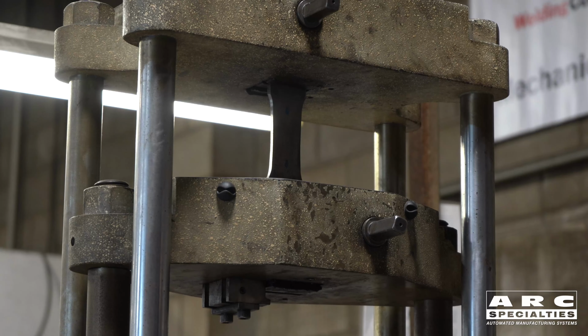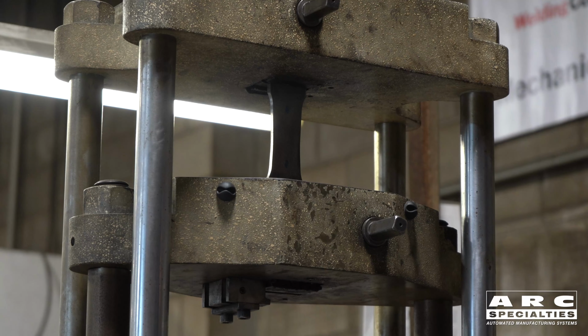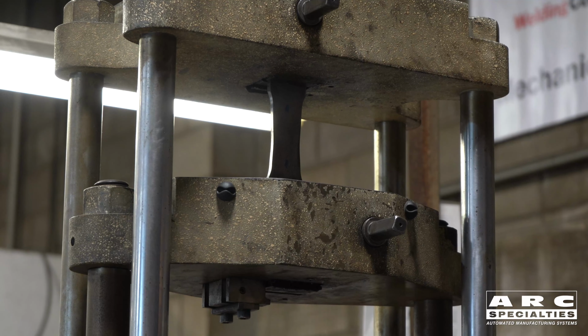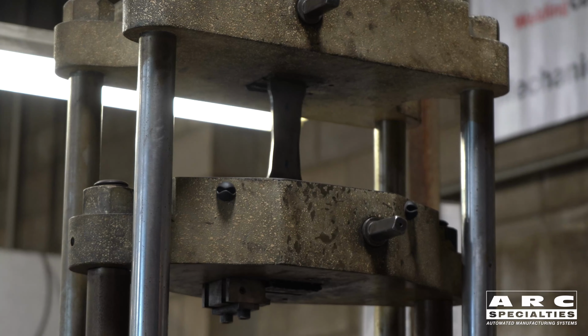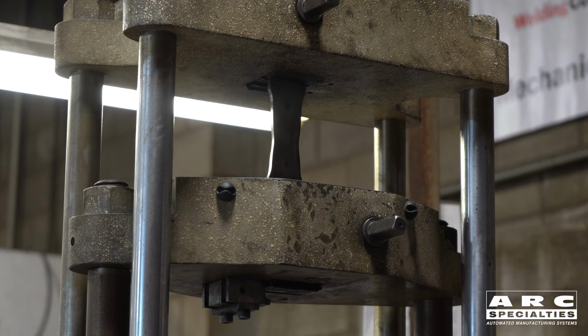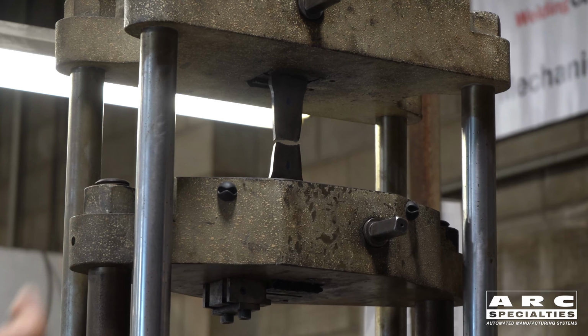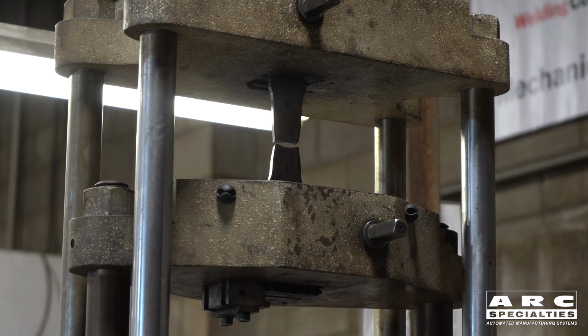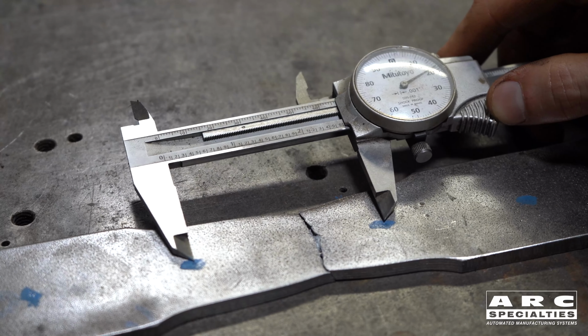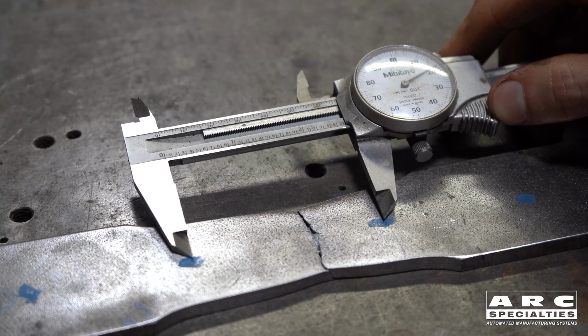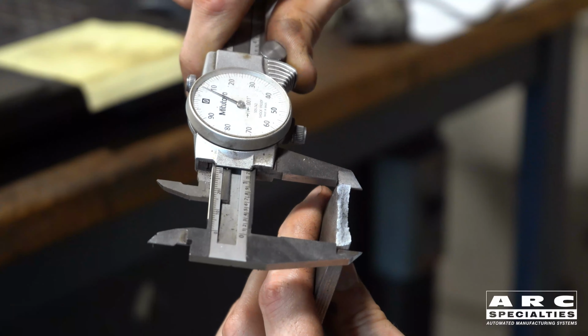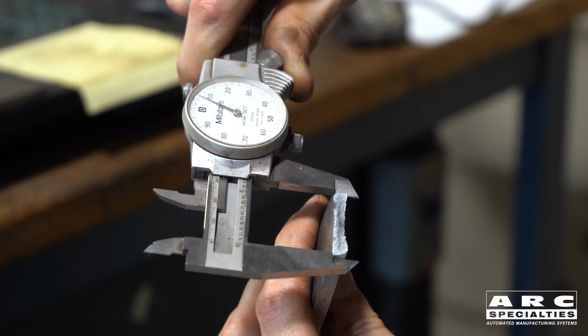So that's one of the other things we're measuring, right, is elongation and reduction of area. That's right. As it gets pulled apart and that elongation is happening, the center of the tensile is actually getting smaller in its cross-sectional area, and that's how we get that pounds per square inch. So this will give us... there it went. That gave us some determination of ductility. We saw decent elongation and good reduction of area. So this is not a brittle part at all, is it? That's right. This is one of the more ductile parts I've tested.